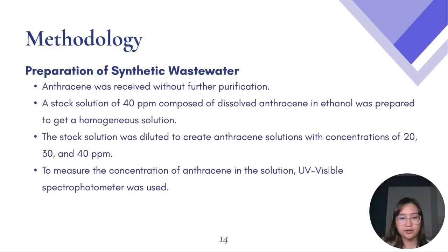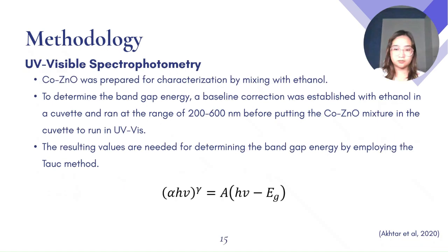For the preparation of synthetic wastewater, anthracene was used without further purification. A stock solution of 40 ppm composed of dissolved anthracene and ethanol was prepared to get a homogeneous solution. The stock solution was diluted to create anthracene solutions with concentrations of 20, 30, and 40 ppm to create the working solutions that will be used in the photocatalytic degradation tests. To measure the concentration of anthracene in the solution, a UV-visible spectrophotometer was used.